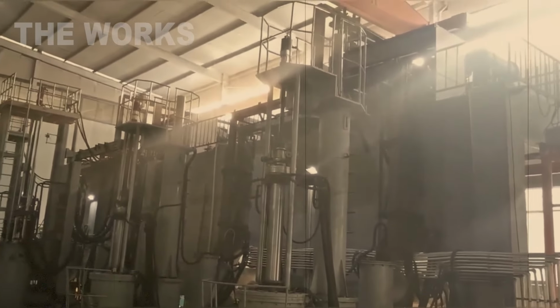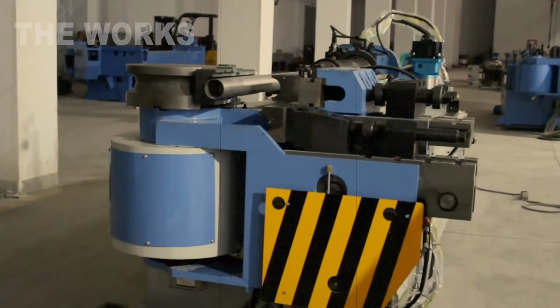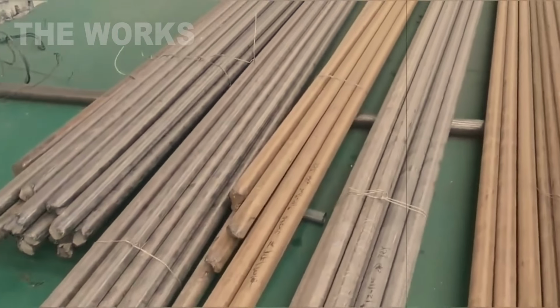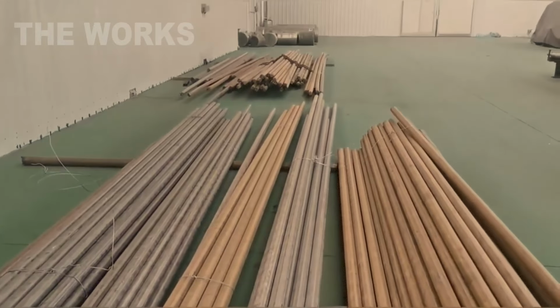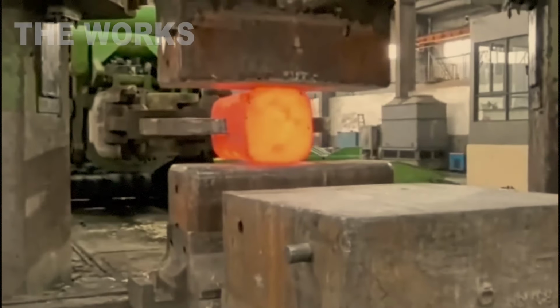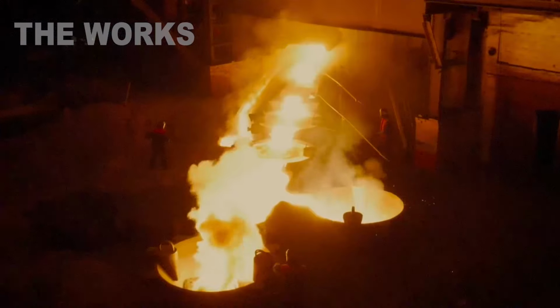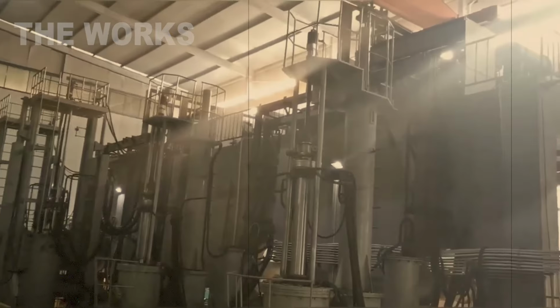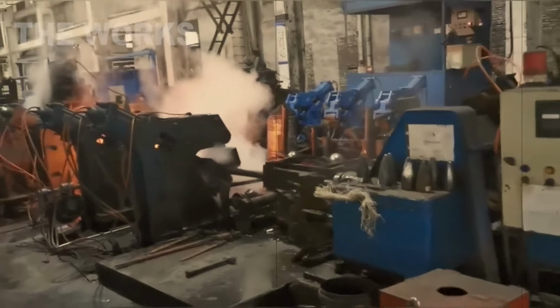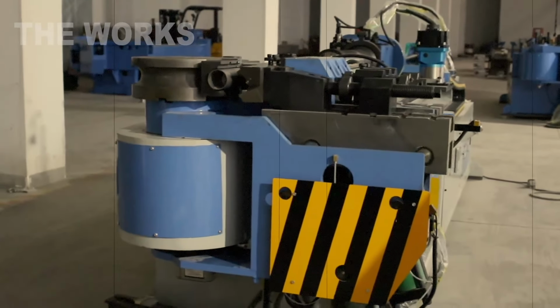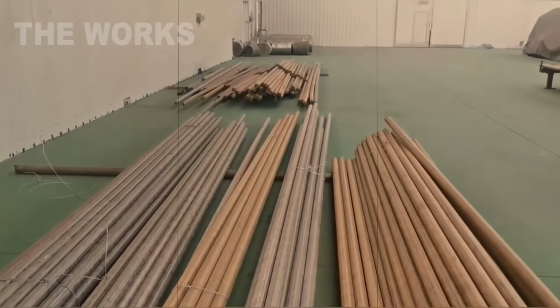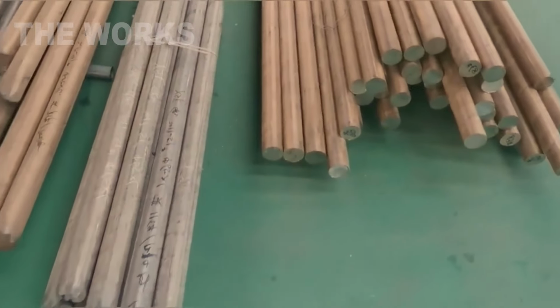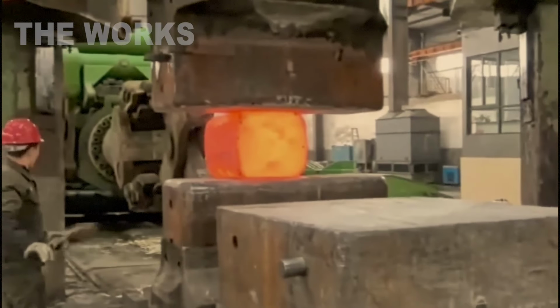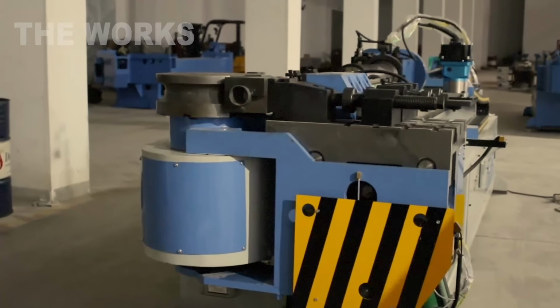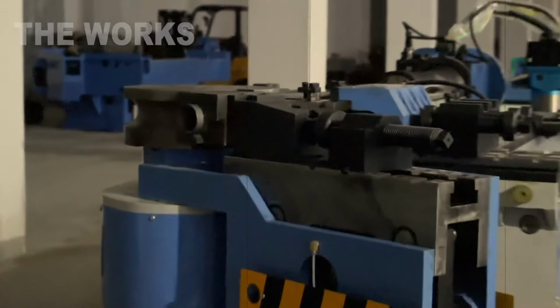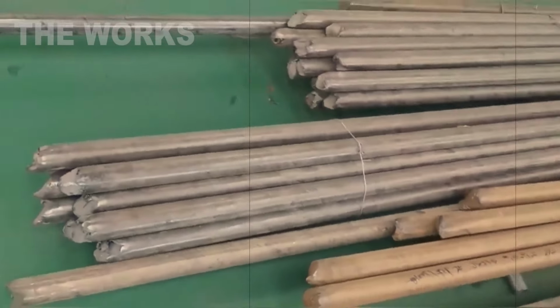This is necessary because at high temperatures, titanium absorbs oxygen and nitrogen from the air with incredible greed, instantly making it brittle. Inside a sealed chamber, a powerful electric arc, like lightning, melts the briquettes, and liquid titanium flows into a copper, water-cooled mold. To achieve perfect uniformity, this process is repeated twice, sometimes even thrice. The result is a gleaming, silvery ingot of pure titanium, ready for further processing. Just look at this incredible transformation, from porous, lightweight sponge to dense, shining metal.